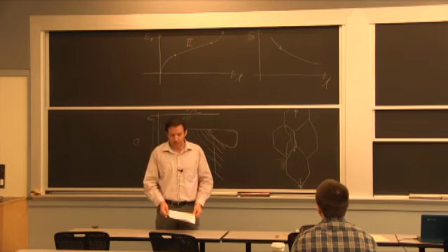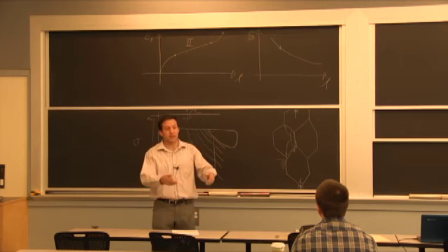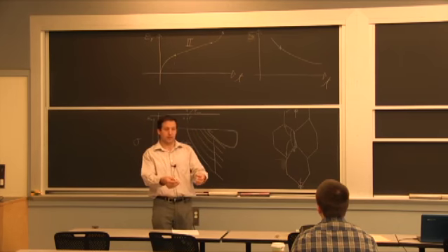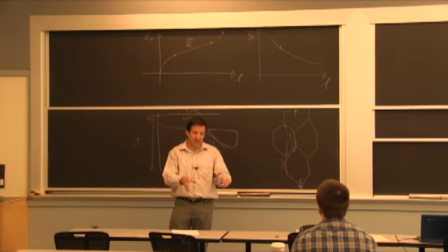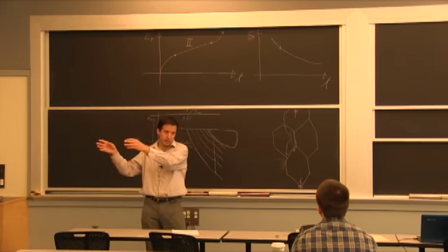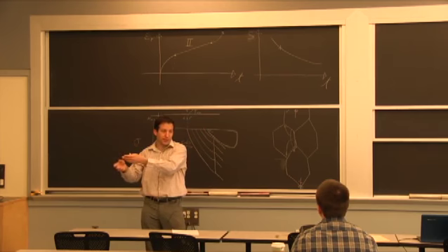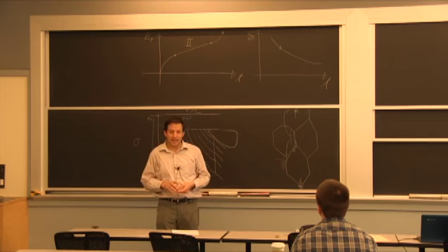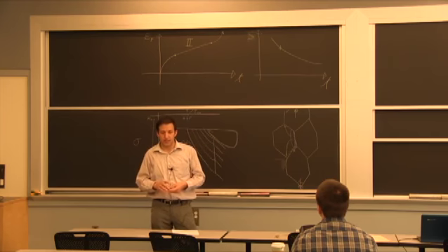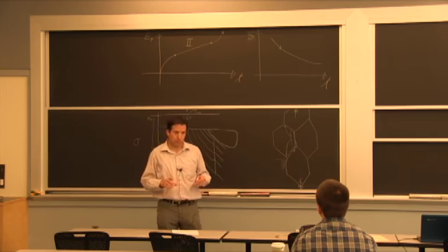It's not so much that, it's a plastic deformation process, because you really have the dislocations moving. But what happens at the same time, in another location, 2 other dislocations get back together. And that's why I don't really want to call it elastic, because there's a permanent change.